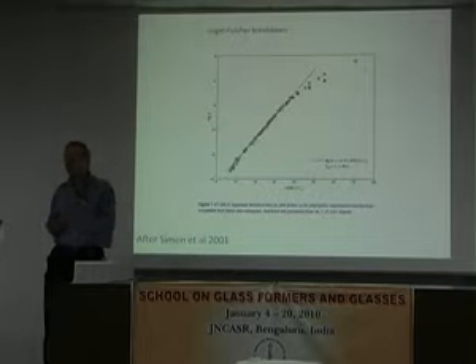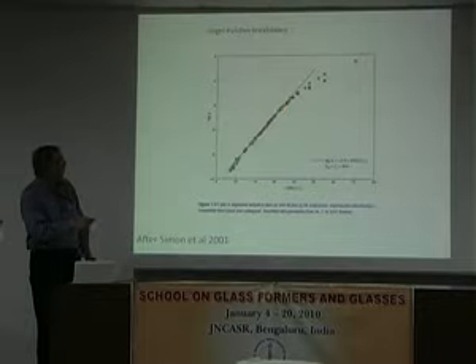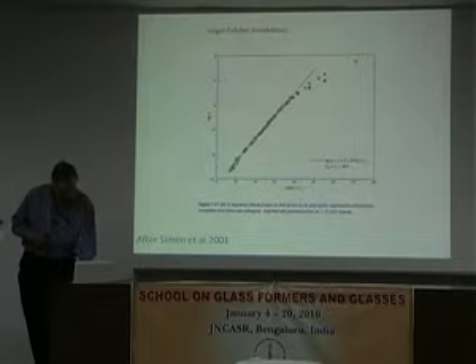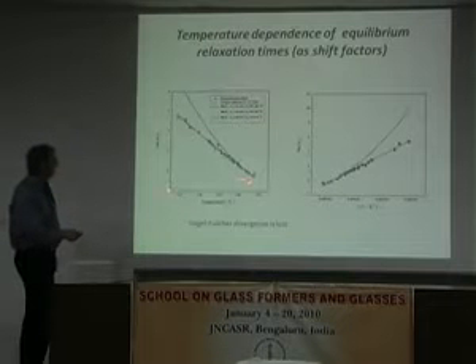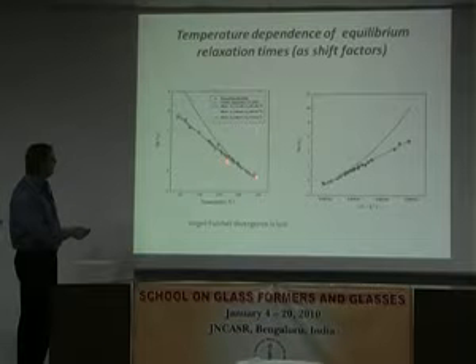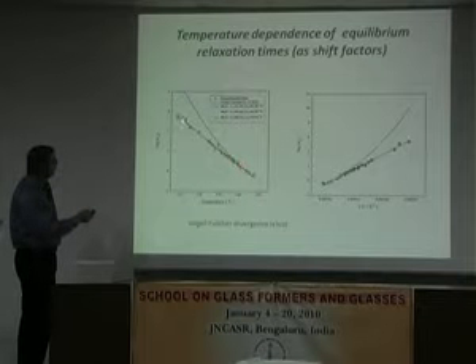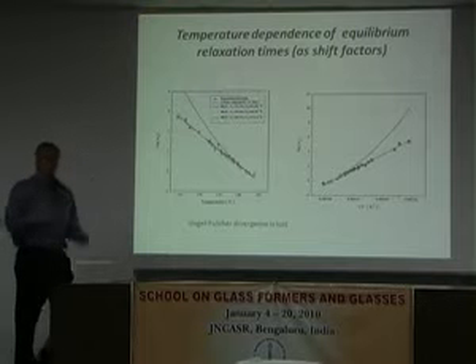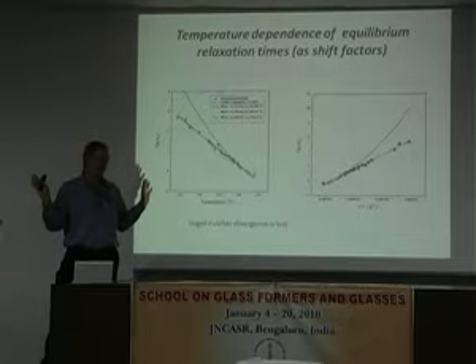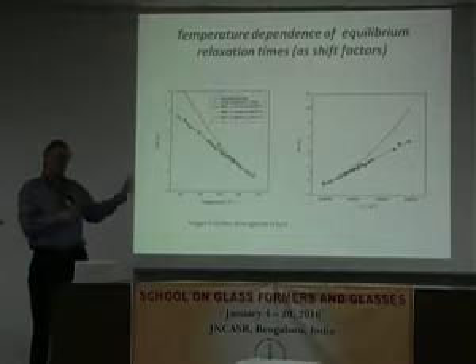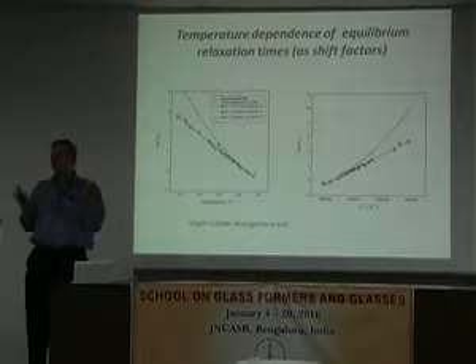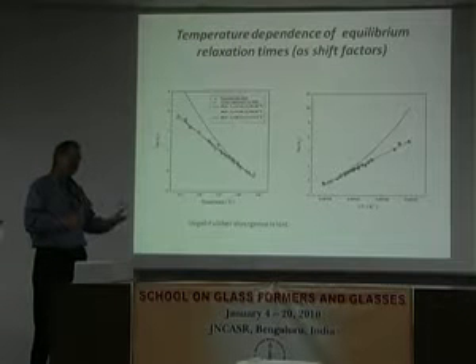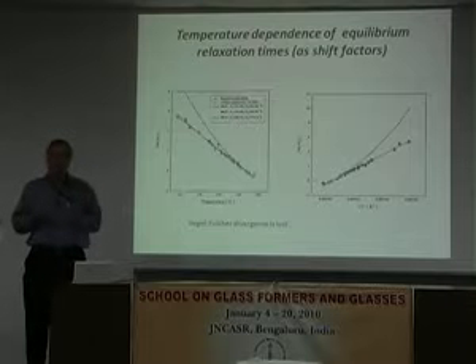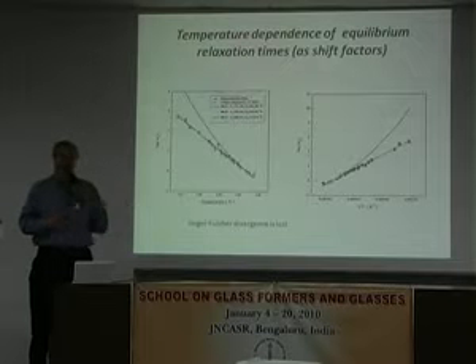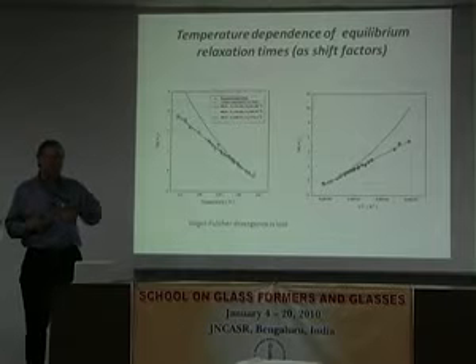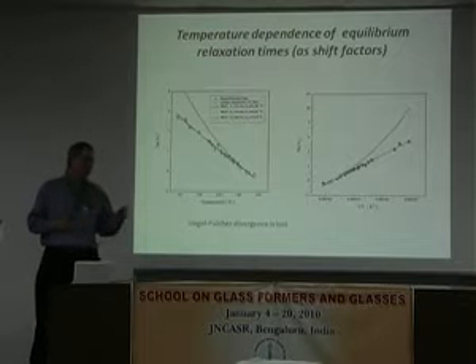If there's a divergence, of course, these are still limited temperature regimes. This is a limited temperature regime. It's conceivable that this just represents some other divergence that there's no way I can measure, okay? But it's important to know that we can do this experiment, and if you're patient, you can do these experiments and find out whether or not the material will fall into that regime. Now, we've tried to do this with some small molecule glass formers, and we keep running out of liquid nitrogen, so we can't age them in equilibrium, right?